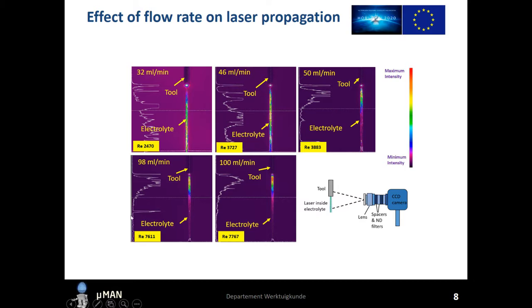But as we increase the flow rates, the Reynolds number approaches the turbulent regime, and the electrolyte behaves like a spray, and we lose the alignment. Also, if the flow rates are higher, we get more convection cooling, and then the laser heat is not getting into the workpiece surface in proportion to what we applied, so the power efficiency is not that good.